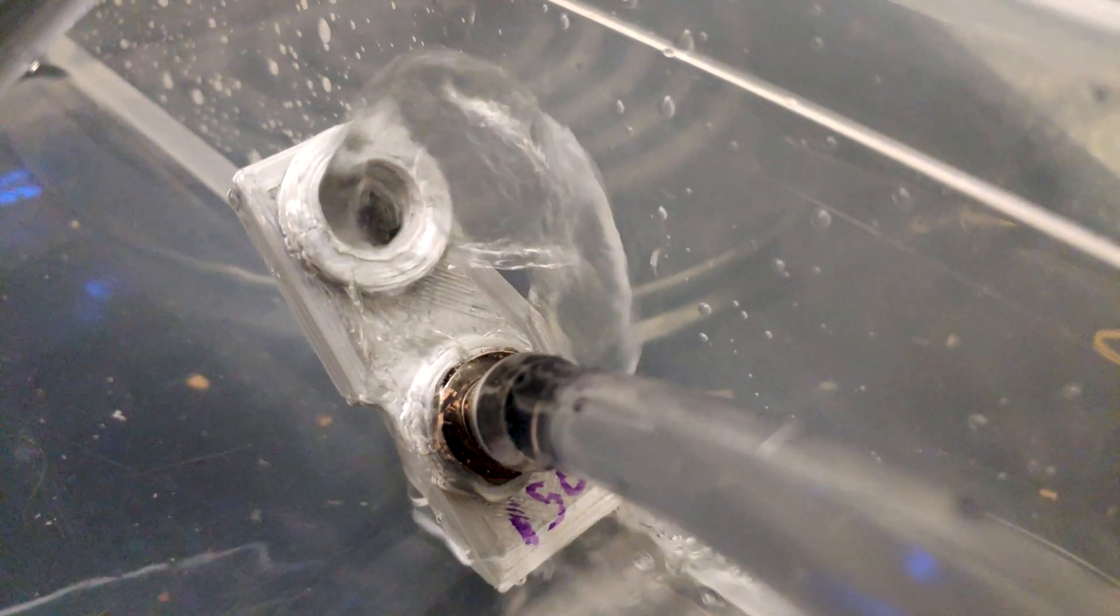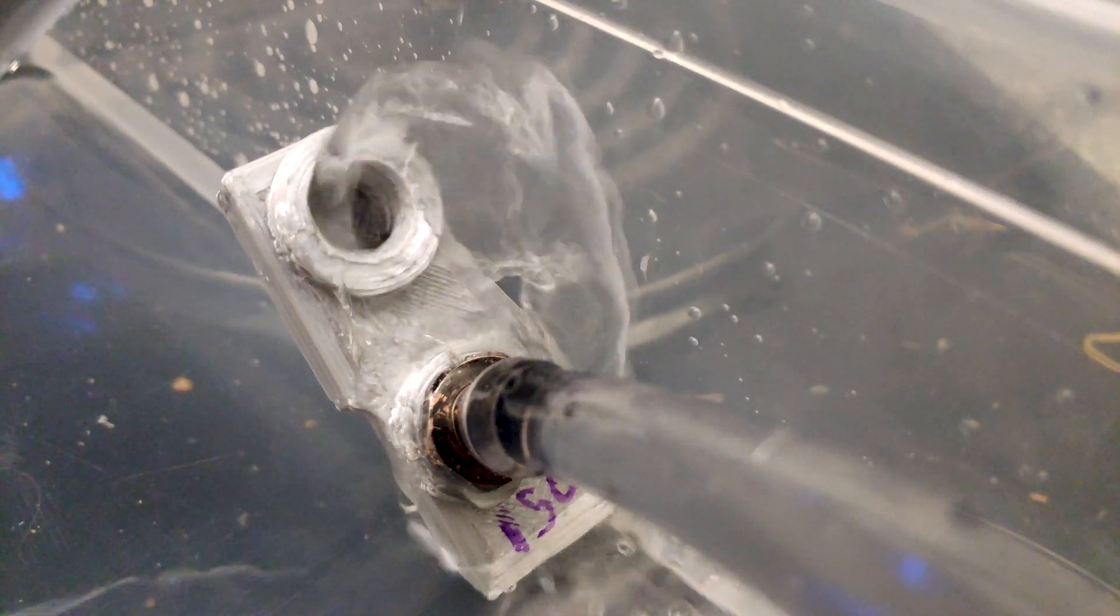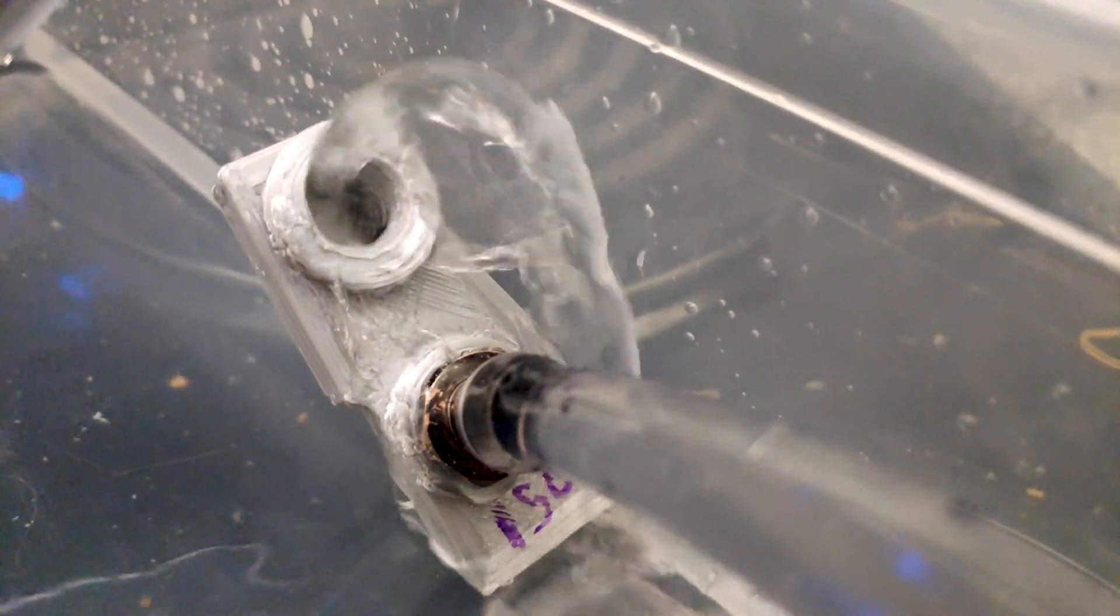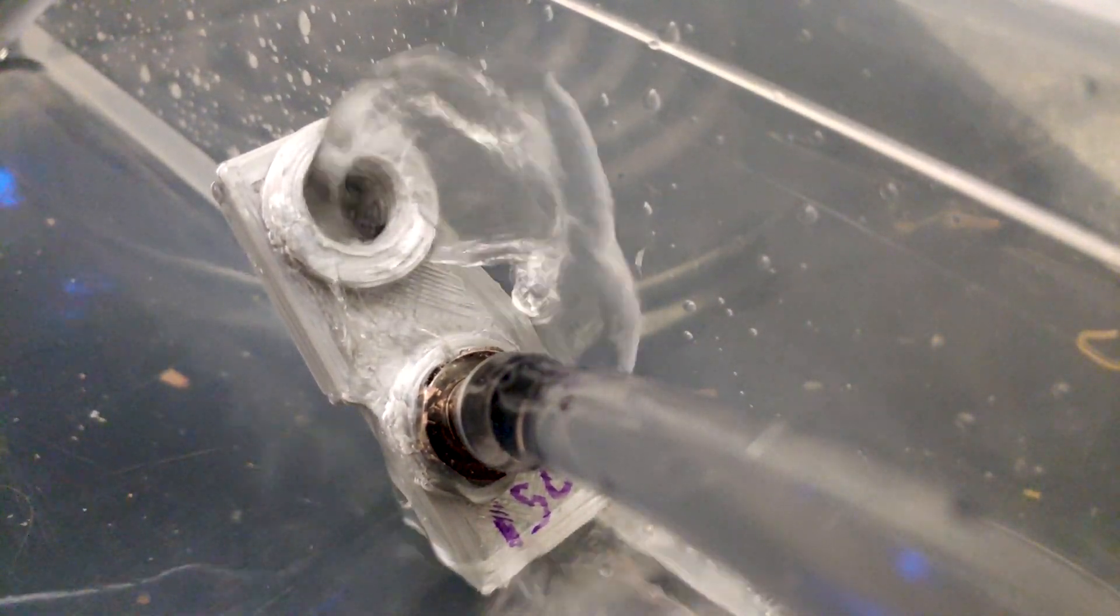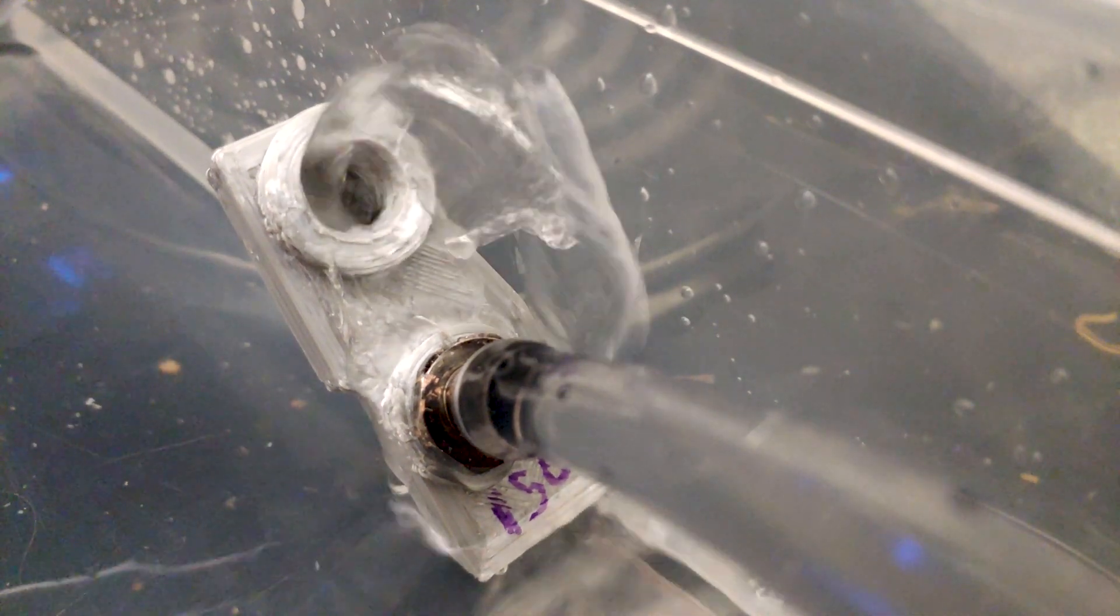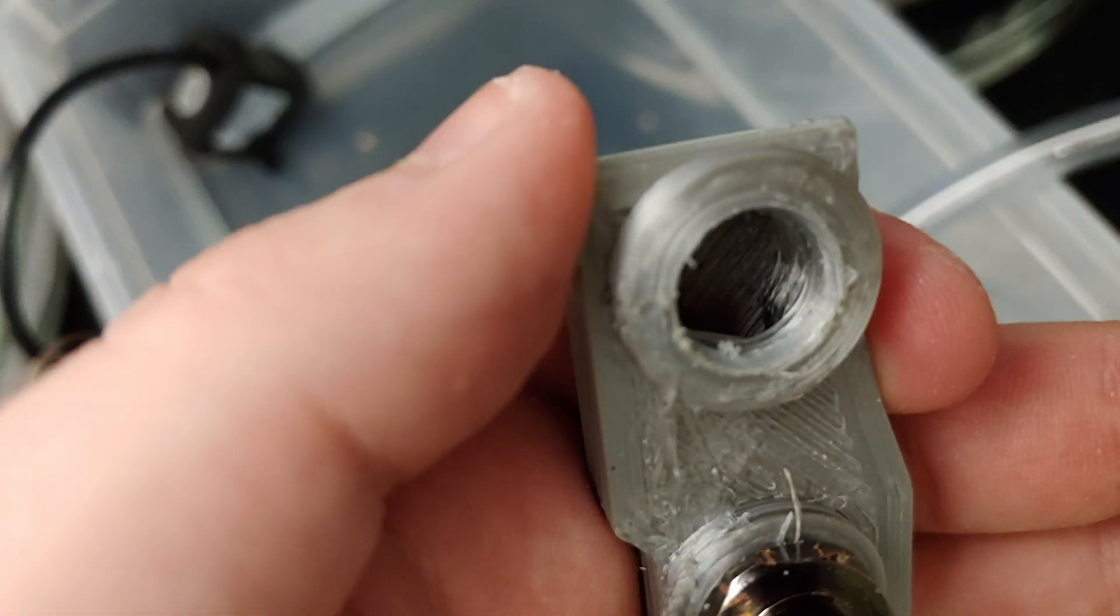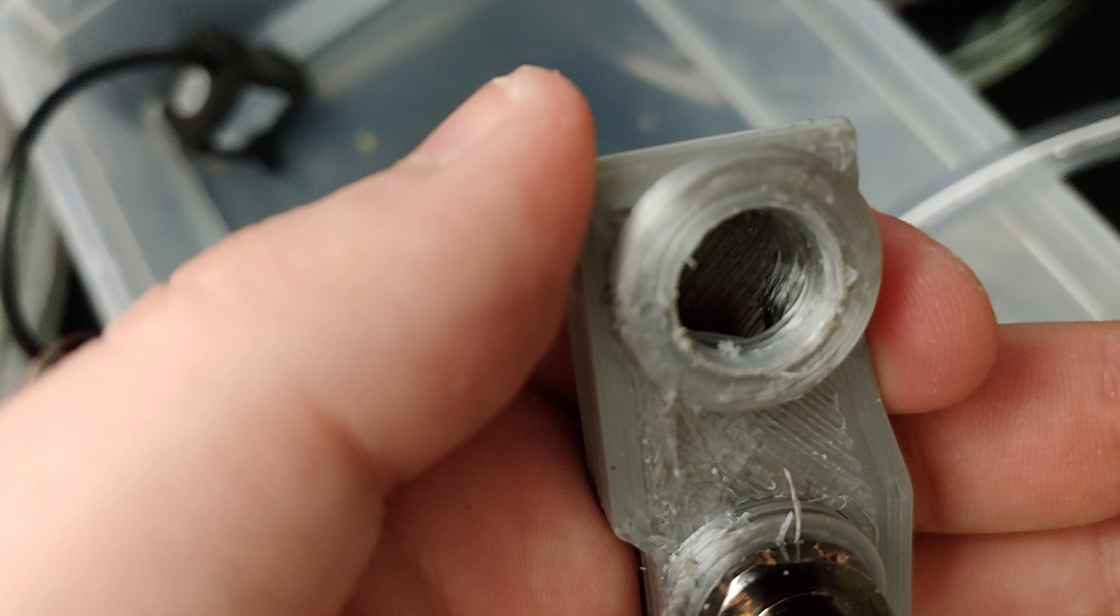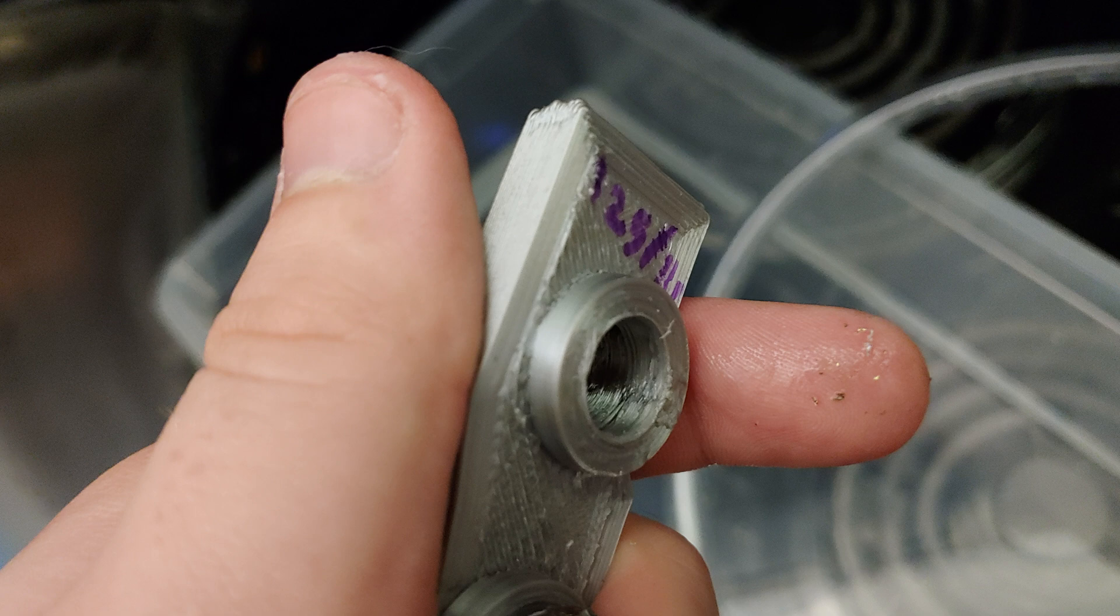Besides being the ugliest duckling of the group, the 150% extrusion model was so over-extruded that I couldn't even get the second barb fitting on it. I gave up after about 20 minutes of just trying to screw in the second barb fitting. You can see that the plastic is pretty torn up from the threads of the screw, and you can see here that I managed to scrape off some of the nickel coating on those fittings as well. Overall, not a good experience.